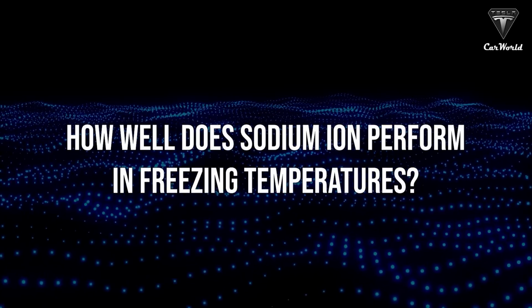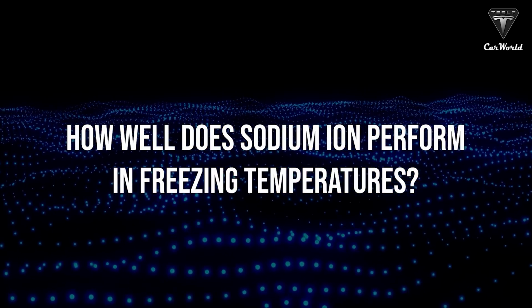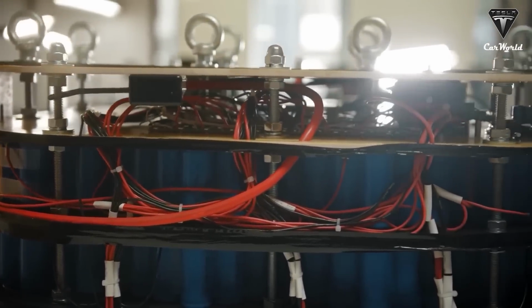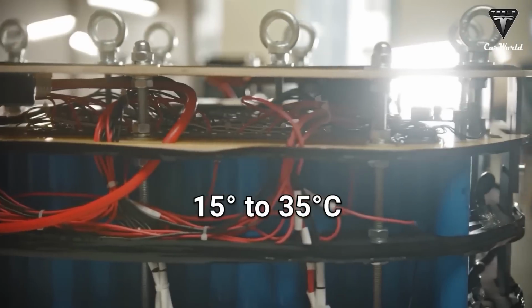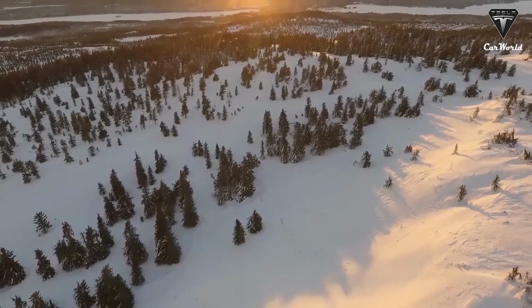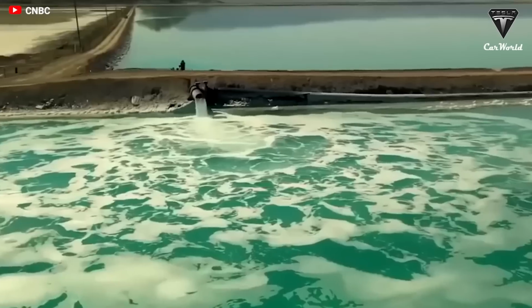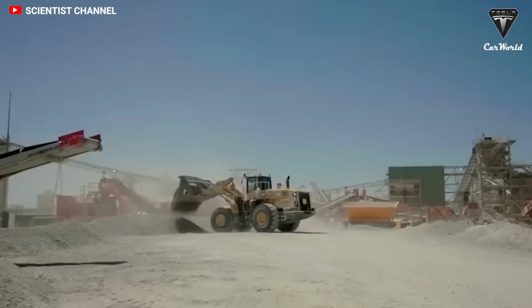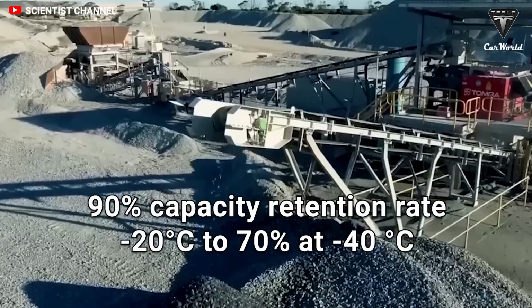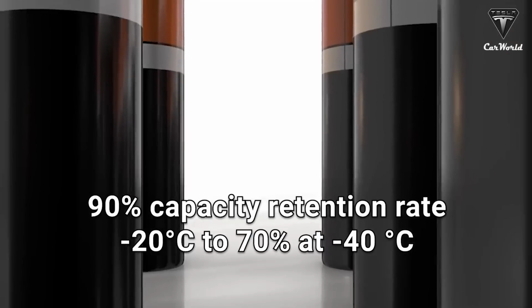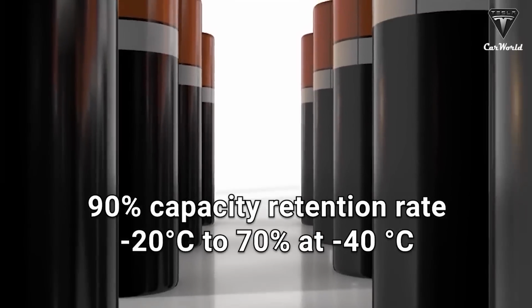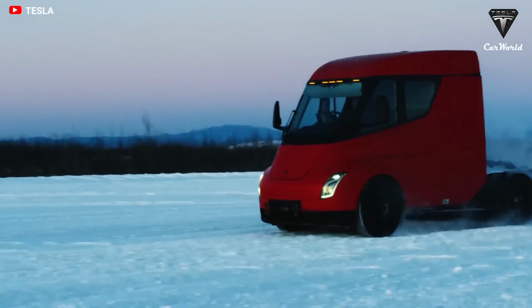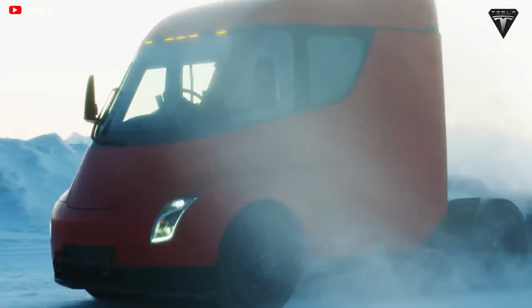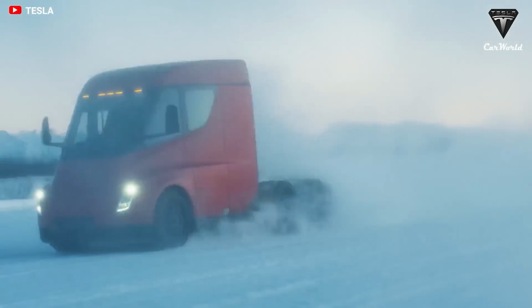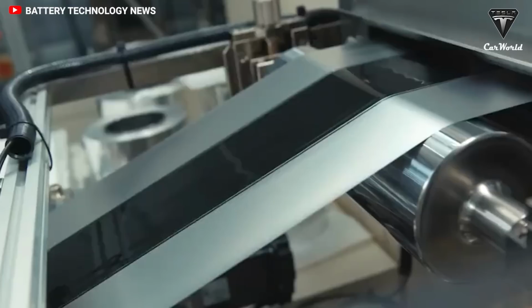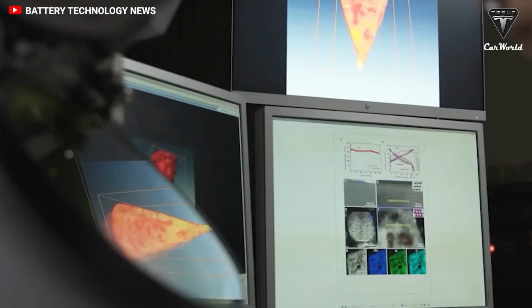Now, how well does sodium-ion perform in freezing temperatures? Lithium-ion batteries can only function optimally at 15 to 35 degrees Celsius, which is why they are problematic in the wintertime. CATL's sodium-ion battery will sustain a 90% capacity retention rate at negative 20 degrees Celsius and still has a retention rate of more than 70% at negative 40 degrees Celsius. In winter, the problem of electric vehicles' inability to cruise will no longer be apparent. Also, we haven't seen anything that says there is a significant degradation at higher temperatures either.